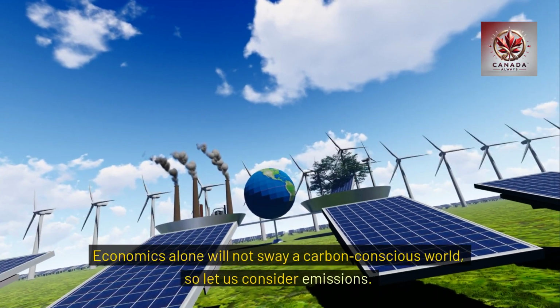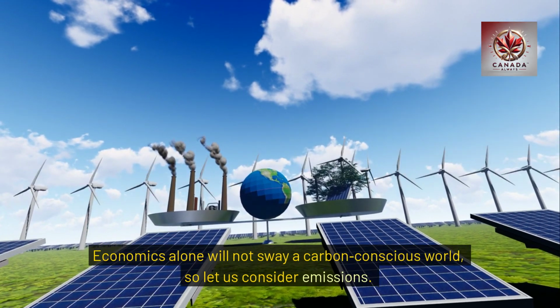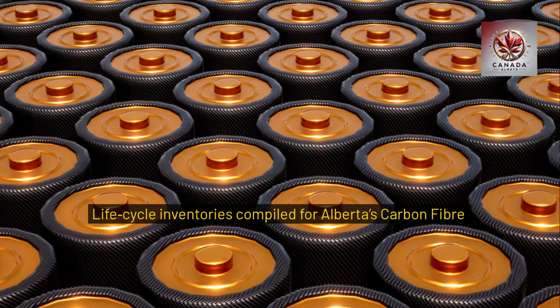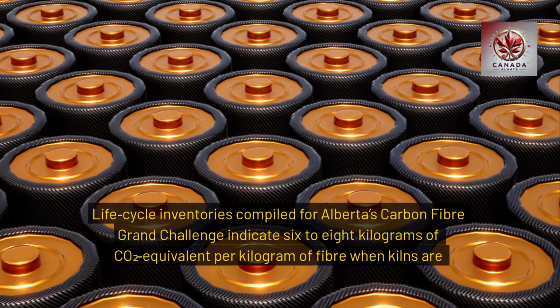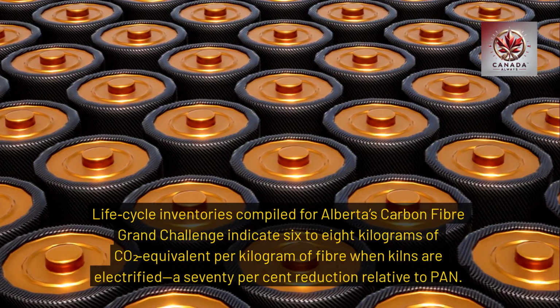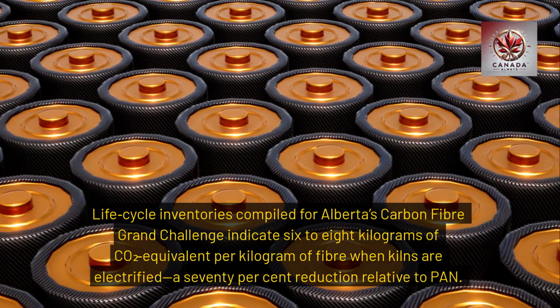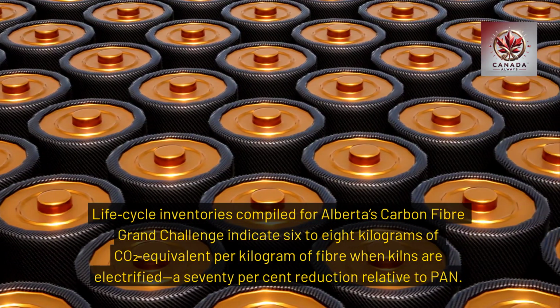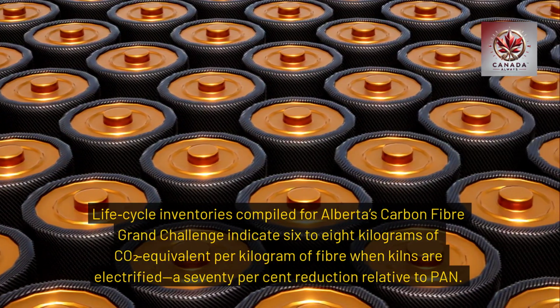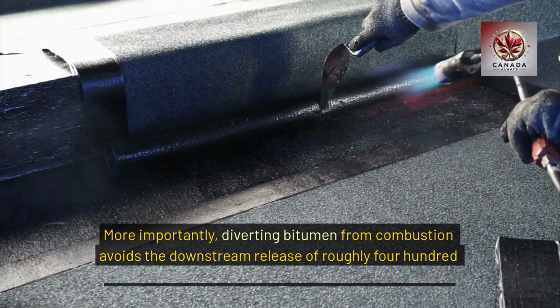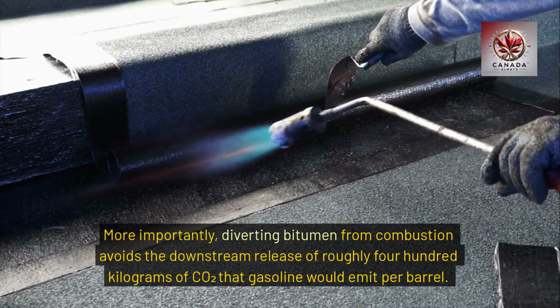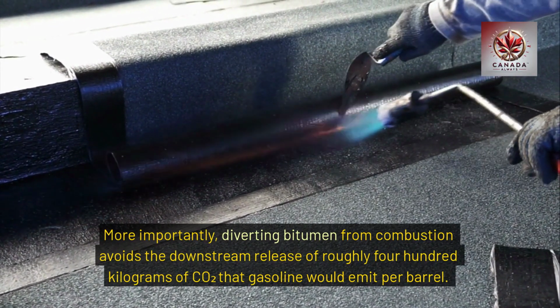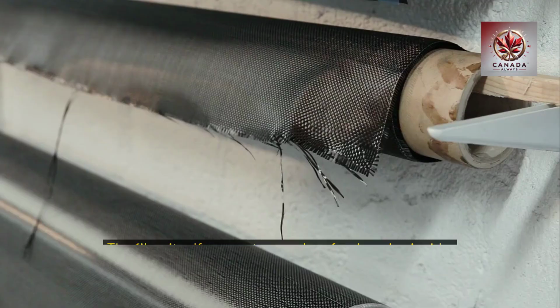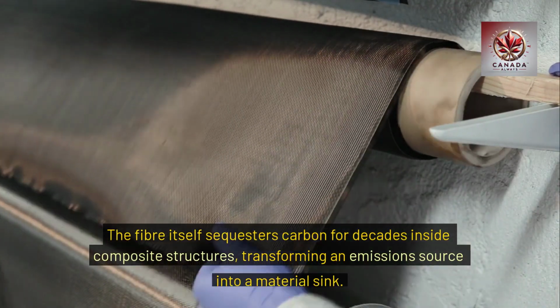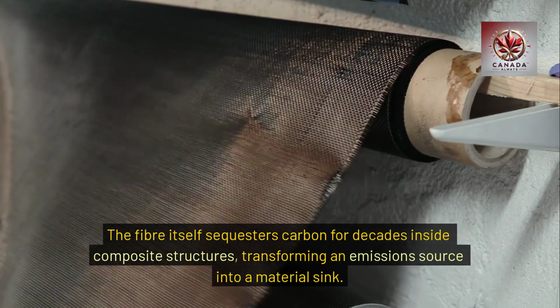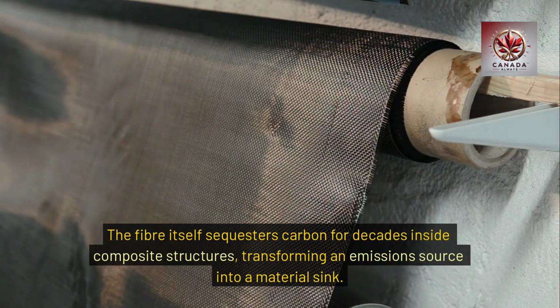Economics alone will not sway a carbon-conscious world, so let us consider emissions. Life cycle inventories compiled for Alberta's Carbon Fiber Grand Challenge indicate 6 to 8 kilograms of CO2 equivalent per kilogram of fiber when kilns are electrified, a 70% reduction relative to PAN. More importantly, diverting bitumen from combustion avoids the downstream release of roughly 400 kilograms of CO2 that gasoline would emit per barrel. The fiber itself sequesters carbon for decades inside composite structures, transforming an emissions source into a material sink.